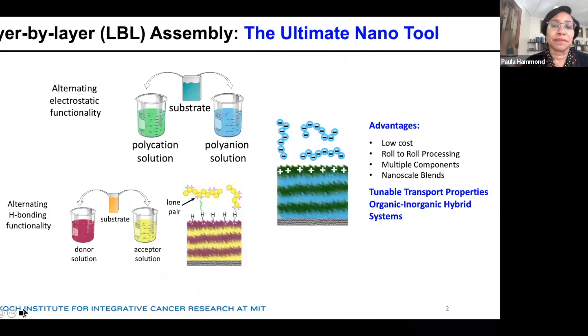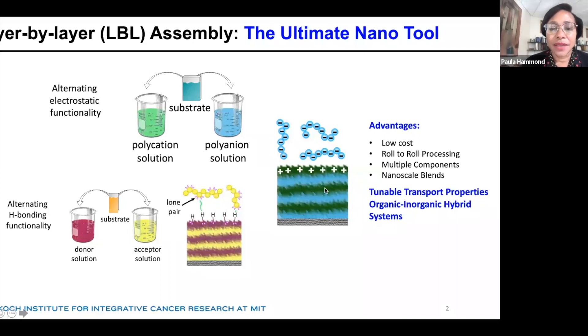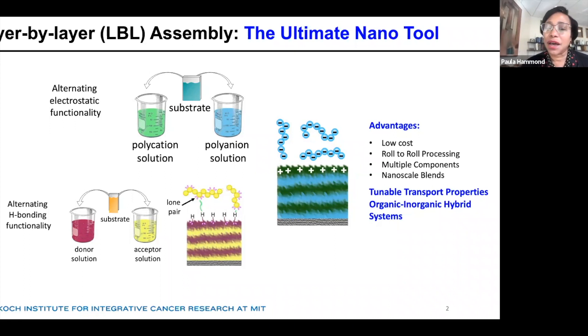At that point you have electrostatic repulsion, and you have a monolayer that has been generated. You can then dip the same substrate into a dilute aqueous solution containing the oppositely charged system, and continue this alternating adsorption process until you build the thin film that you desire. You can incorporate a range of different material sets into these layers — from nanomaterials to biologics such as proteins and nucleic acids, all of which carry a native charge. We can even incorporate small molecule drugs that are heavily charged or incorporated into charged vehicles.